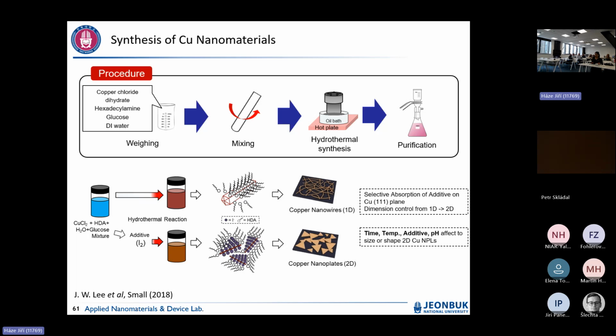This is really simple because we followed conventional nanowire synthesis, but one of my students made a mistake. She put in a very interesting halogen material, iodine, and it dramatically changed the shape from 1 dimension to 2 dimensions. Unfortunately, it took a lot of time to make sure of the right condition, almost 4 or 5 years. Now we got a really nice condition because the halogen material is selectively adsorbed on the basal plane, for example, 1, 1, 1. It successfully suppressed growth in this dimension, and the nanosheet grows only in this plane.